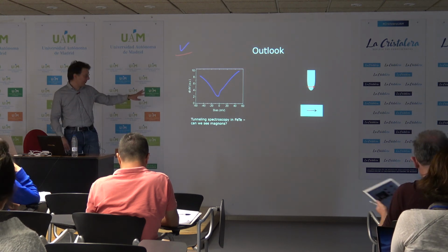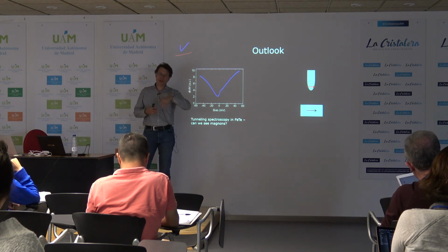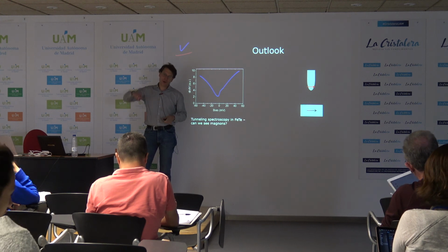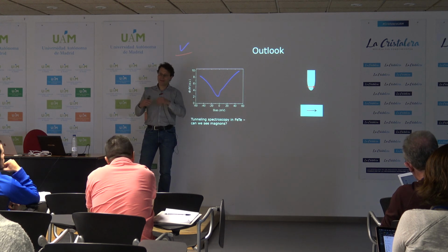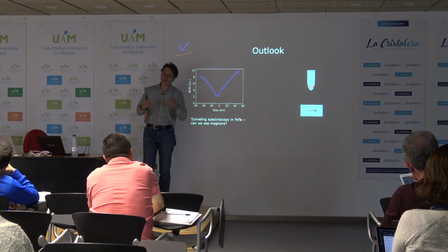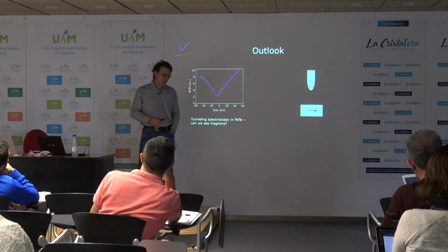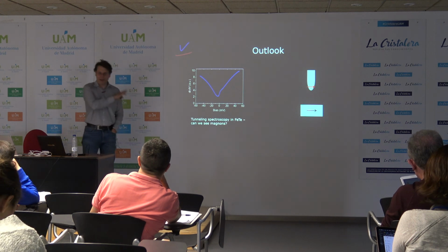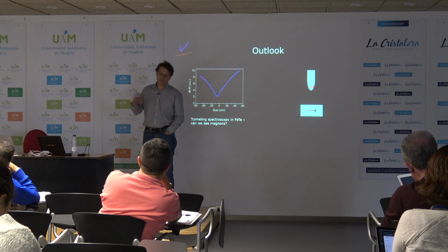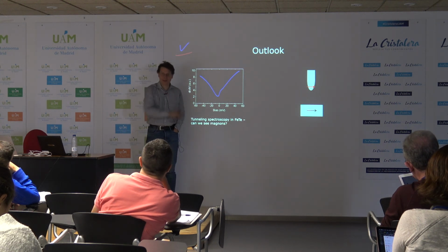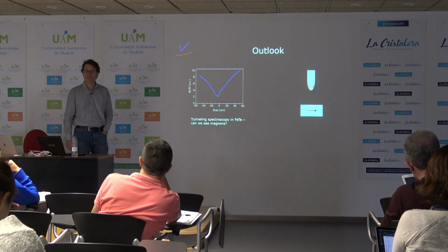For example, when we make these magnetic tips by collecting iron, before it's actually stable magnetic, at some point you start to see that the tip magnetization fluctuates, so we see the magnetic order very noisy before it becomes a properly stable magnetic cluster. But there are people who do time resolved measurements in a kind of pump probe way, which is not what we are doing, and there you can get much higher time resolution.